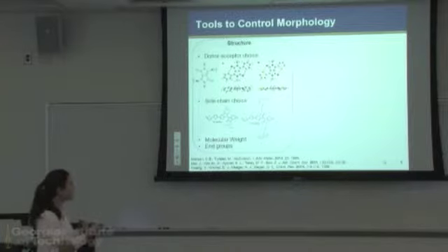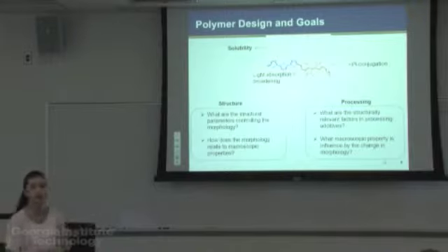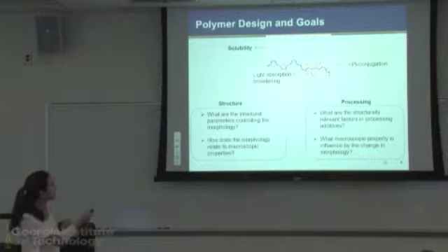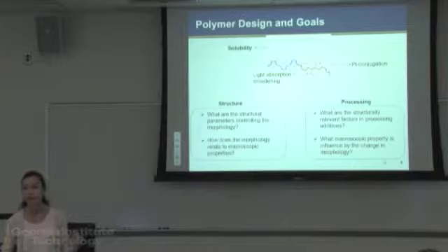So the polymer system that we're using throughout the study is this terthiophene coupled to isoindigo. So we have the electron-rich unit and then the electron-poor unit alternating, so that gives us the light absorption properties that we want for organic photovoltaics. And in the first part, we're playing around with the side chain on the terthiophene unit in order to modify the solubility of the resulting polymer.